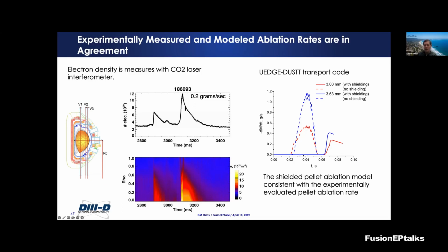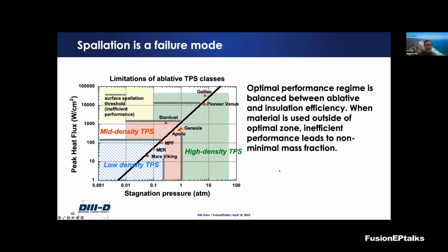Then we got the solid lines here, the solid red and solid blue, for two sizes of pellets of 3 and 3.6 millimeters. Those numbers were now giving us something like 0.2 grams per second, quite comparable to what we had in the experiments. Nice, good result.